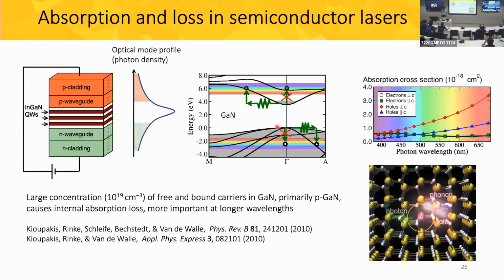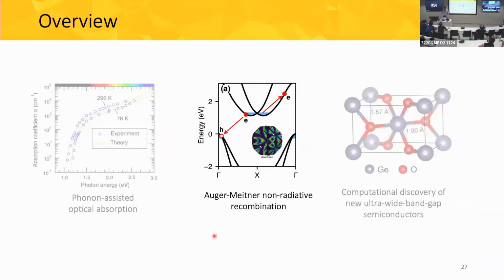And again, going back to the work on the nitrides I did back in my postdoc, the same thing applies also in semiconductor lasers, where in the laser, the light bounces back and forth in the doped regions of the laser, where it can be absorbed by electrons or holes. And by accounting for how holes can absorb visible photons, we can explain the internal loss in nitride lasers at high power. All right.